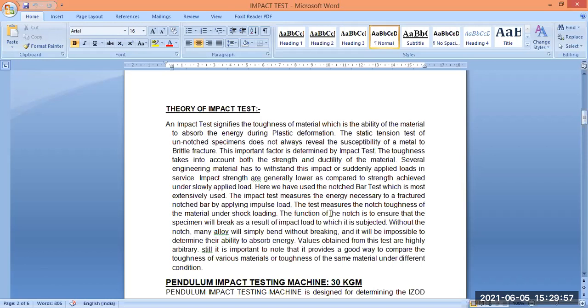The test means the notch toughness of the material under shock loading. We have used the notched bar test, which is most extensively used. The impact strength is generally lower compared to the strength achieved under slow loading, but the difference is also there.